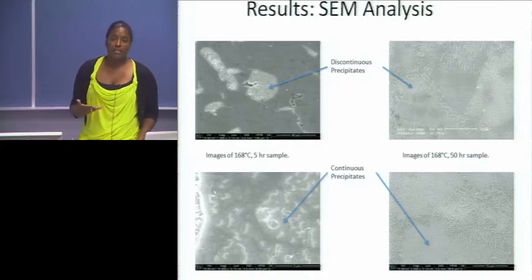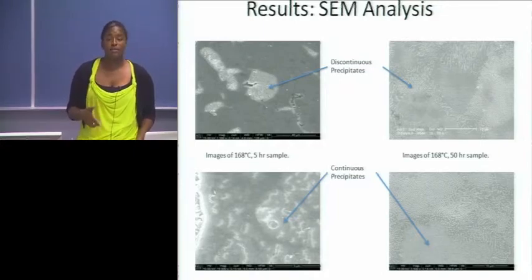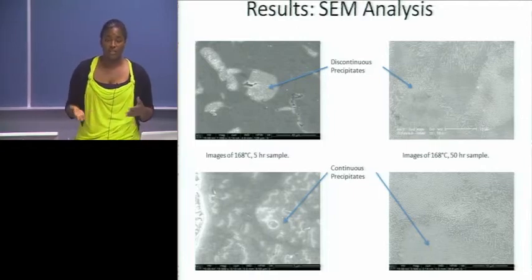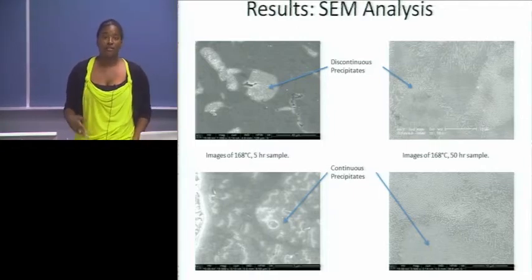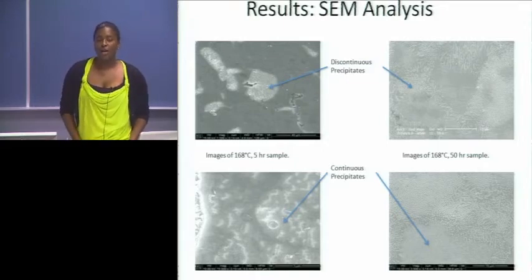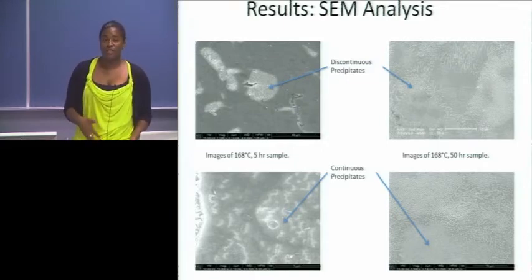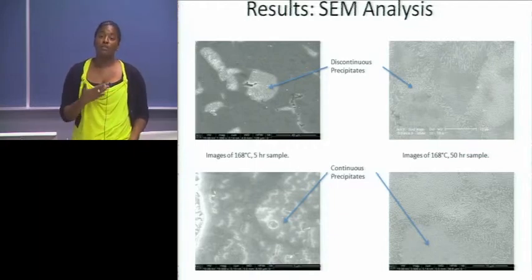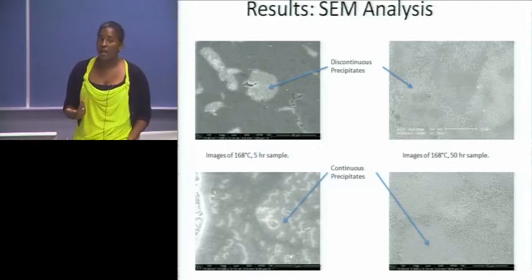In future work, I would like to look at these microstructures under a TEM so that I could see the orientation difference in atoms, and that could help me identify whether it was twinning or dislocation slip. And also in future work, I would like to perform XRD so I could quantitatively identify how much the beta phase precipitates increased in the samples with aging time. So that was my project this summer.